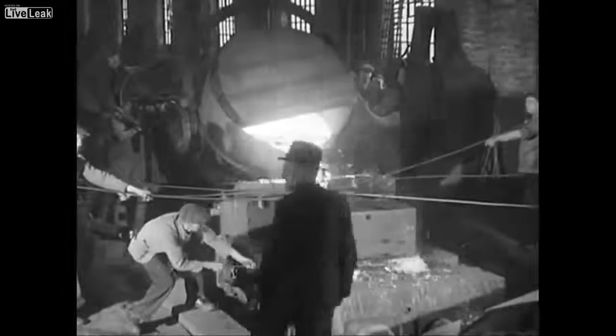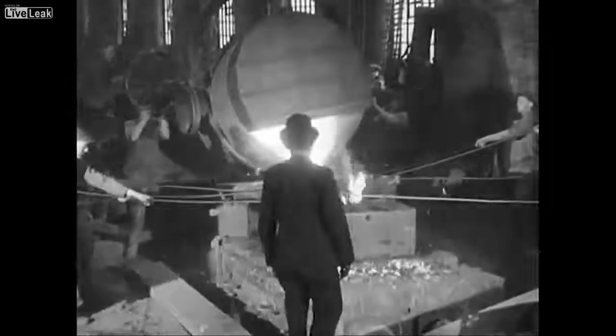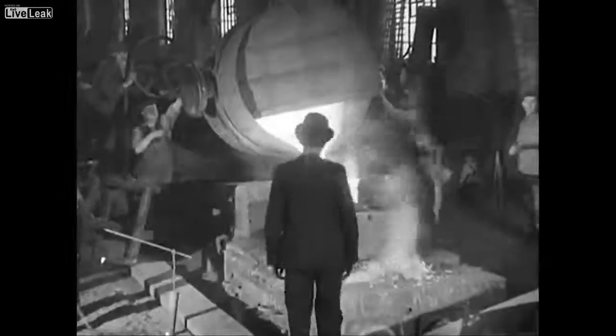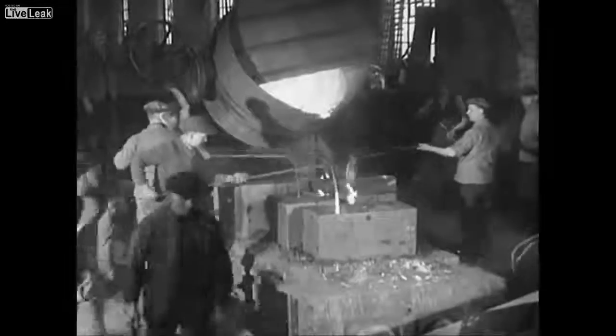The foundry foreman takes up his position, and carefully watching gives the signal to pull the plugs immediately the cast is complete. This allows the gases given off by the hot metal to escape. Metal may set too quickly near these plug holes, and these men carrying out an operation called feeding are preventing this from happening.